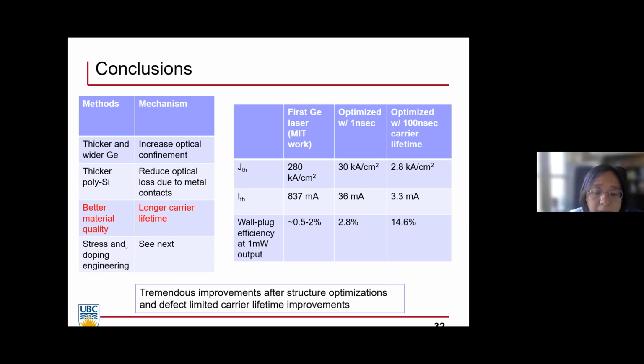That was another publication related to this. So basically, if we use all these tricks, we can significantly reduce the lasing threshold by about 100 times. And wall plug efficiency can be improved to about 15%.